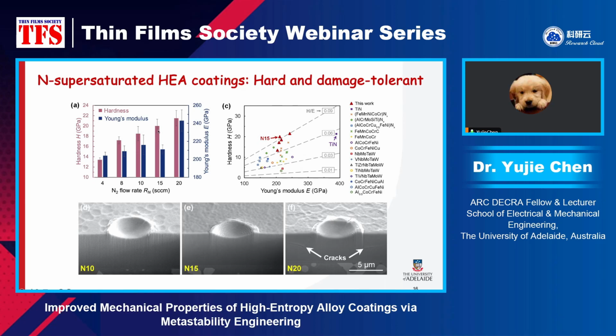As we can see, this hardness is around 20. We know the hardness of titanium nitride is around 20. So it's not yet nitride. This N15, it's still a metal coating, but its hardness is comparable to ceramics. And at the same time, it didn't show any cracks. It showed large plasticity. We know that titanium nitride is quite brittle, right? So that means this one is not only strong, but also tough.